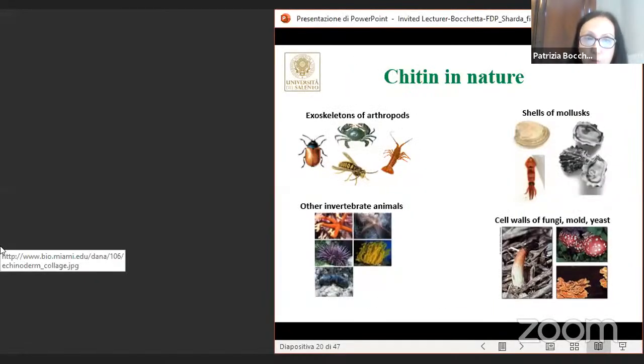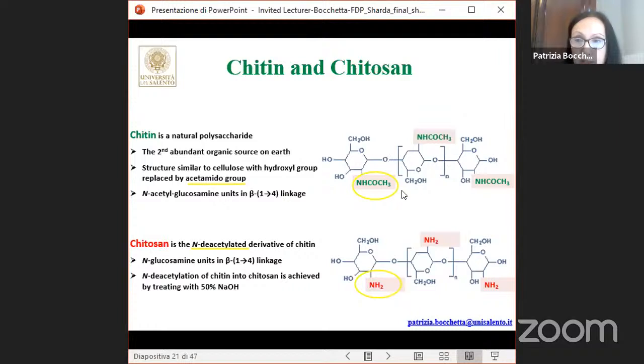As told before, chitosan is a renewable material, and it is derived from the alkaline deacetylation of chitin, one of the most abundant natural polysaccharides on Earth, usually found in crustacean shells, insects, molluscan, and fungal mycelia. Nowadays, the principal source of chitin is shellfish waste. Chitin has a structure similar to cellulose, as you can see here, with hydroxyl groups replaced by acetamide groups. Chitosan is the N-deacetylated derivative of chitin, obtained by treatment with 50% sodium hydroxide.